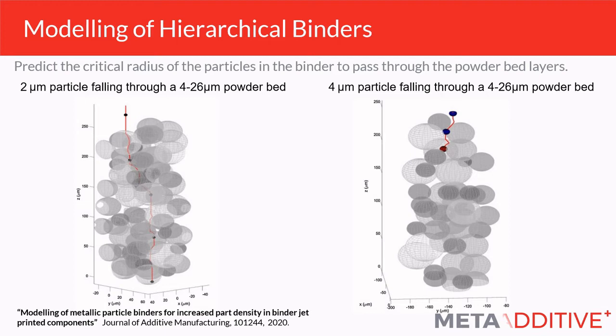So what we see on the right hand side here is a simulation of a powder bed, with a particle being dropped onto that powder bed. If the particle's too large, it will get blocked. It gets blocked halfway down the layer of powder, which would be no good for us, and it would have a detrimental effect on our overall porosity and density of the component.